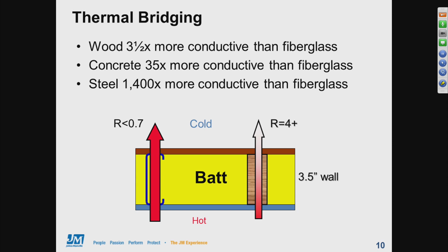To help reinforce this just a little bit more, wood, concrete, and steel can all form thermal bridges because they all conduct heat much better than insulation. So for comparison, wood is about 3.5 times more conductive than fiberglass insulation. Concrete is about 35 times more conductive than fiberglass, and steel is 1,400 times more conductive than fiberglass.